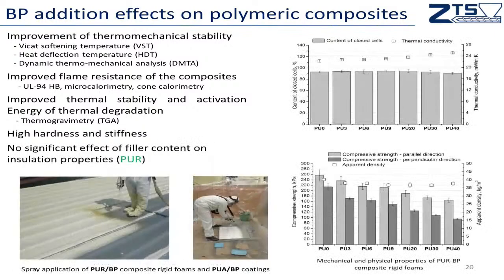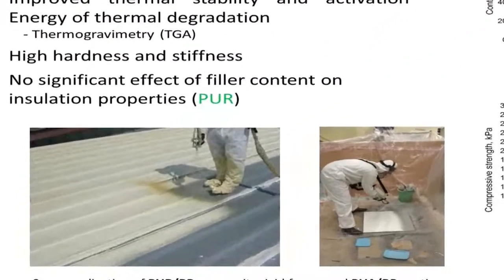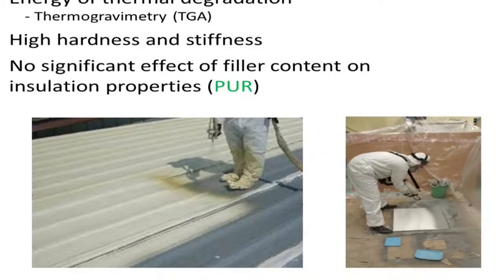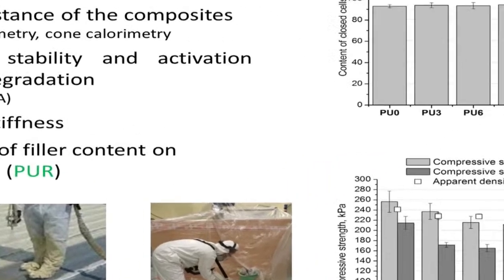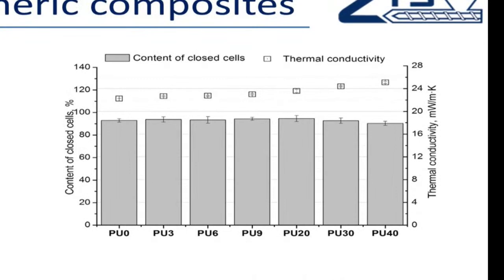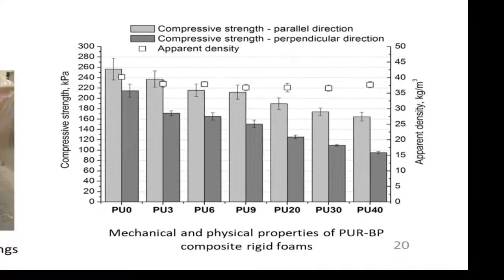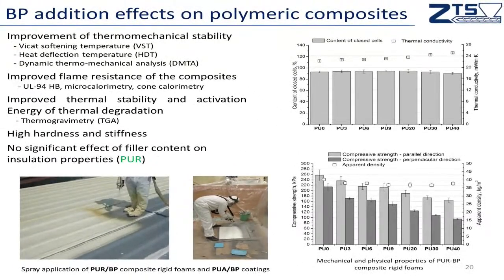And when we move to another slide, I think the most perspective way of utilization of these materials at this moment, as we are working with our industrial partners, as well as the Krakow University of Technology, is development of spray-formed rigid foams for thermal isolation, as well as polyurethane material for reinforcement, to achieve high impact strength materials for pipeline removal. And here we can see on both slides that even with an additional 30% of the filler, and in the top graphs even if we incorporate 40% of the filler, the thermal conductivity is changed, but not enough to exclude this material as a thermal isolating material, due to the partial reactivity of the basalt fibers and changing of the pH of the polyol composition.